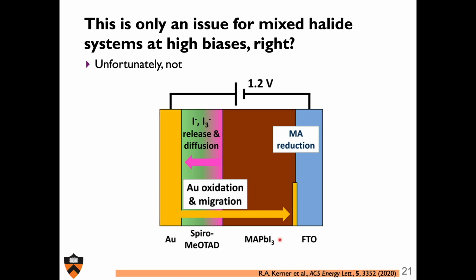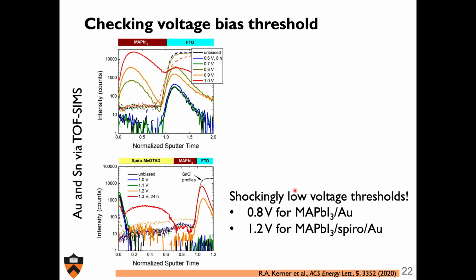And so this is taking the archetypal methylammonium lead iodide. At the anode, I need to worry about iodide oxidation. When I have a hole transport layer, I need to be very worried about the fact that it can react with oxidized iodide. So we'll get to that in a moment. And then for the reduction reaction, I need to be worried about MA reduction, methylammonium being reduced, in which case I've destroyed the system. Total destruction. But I also have to be worried about gold oxidation when I make triiodide, which I will make in a hole transport layer. Triiodide is very easy to make in a hole transport layer. And triiodide is an especially fantastic gold etchant. And so I need to be worried about gold oxidation, and gold reduction at the FTO interface, where it's cathodically biased. And so let's look at the voltage bias thresholds for these different phenomena.